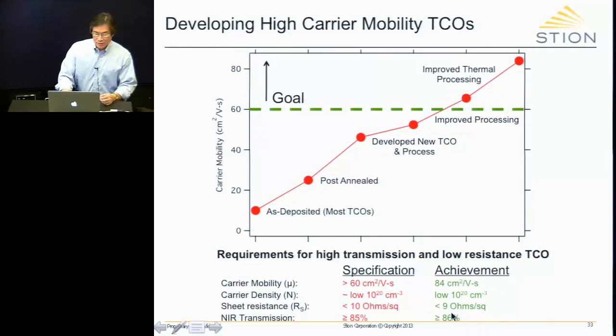And the sheet resistance is at less than 9 ohms per square, and the transmission in the near infrared at 1200 nanometers is greater than 86%. We believe we can get that up to 90. By the way, these numbers are based on as a reference to air.